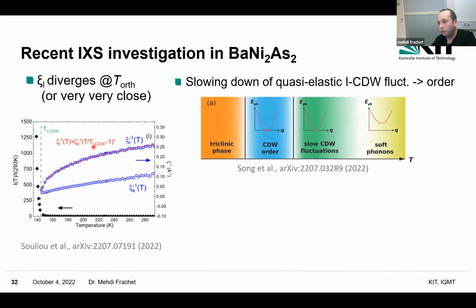Second thing I would like to mention is also this nice preprint by the group of Birgeneau in Berkeley. And what they have seen, still using IXS, is that the formation of this incommensurate charge wave is a two-step process. So first, there is a complete phonon softening, and then you have quasi-elastic incommensurate charge wave fluctuations that slow down to form the charge wave order.